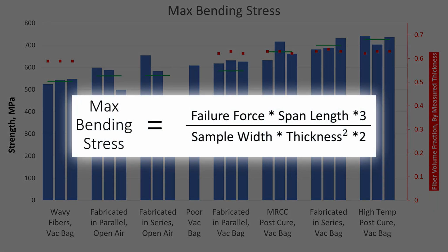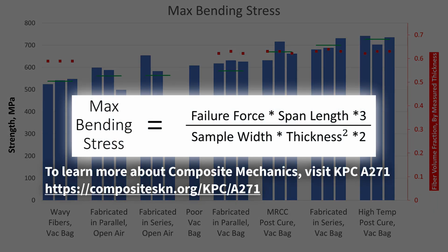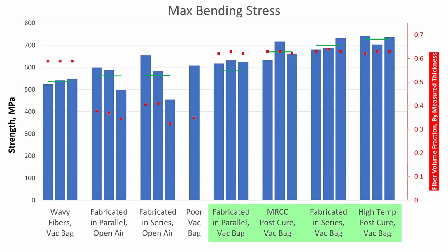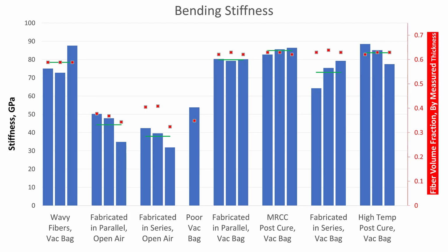Note that the maximum stress is calculated based on the mean thickness of the laminate, so if a thicker laminate reacts the same force as a thinner one, the thinner one will develop higher stresses before failure. In agreement with theory, the vacuum-bagged samples which had higher fiber volume fractions also had higher strengths. The volume fractions are plotted in red according to the right-hand axis. It is notable that the stiffness of the samples varies more than the strength.